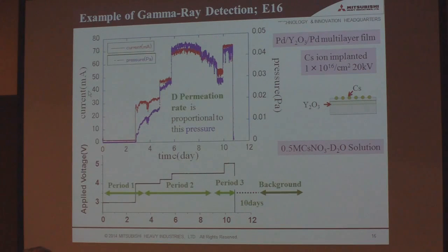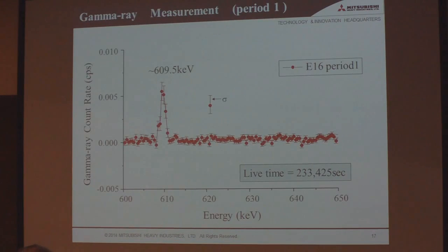We checked that, instead of Y2O3, we get transmutation reactions using this sample. And in this case, cesium is ion implanted like this. We use a 0.5 molar cesium nitrate solution. And we divide the experiment into period 1, period 2, and period 3. And the background measurement is here, and before the measurement, we also measure background.